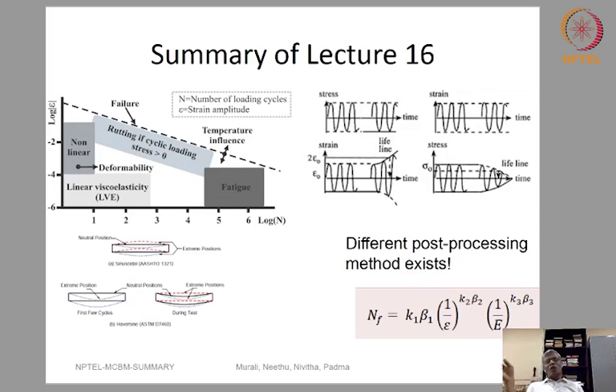Now if you look at the top right picture, you can do this test in terms of stress control or you can do it in strain control. When you do it in stress control, the strain keeps on increasing because you are applying continuous loading cycles. On the other hand, if you do it under strain control, you will see that the stress starts decreasing because the material is getting completely damaged.